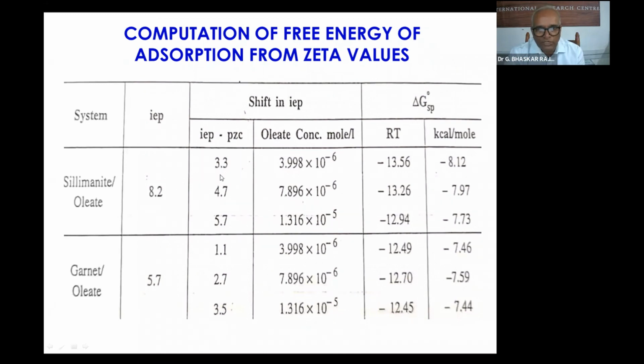So IEP values at different oleic acid concentrations. This is a term, and then you can exactly find out the delta G values. This is 8.12, 7.97, 7.73, like this. In other words, if the delta G is more, say something like 20 kilocalories per mole, then we can categorize it as a specific adsorption, a specific interaction taking place.